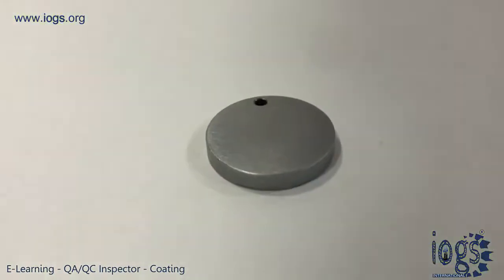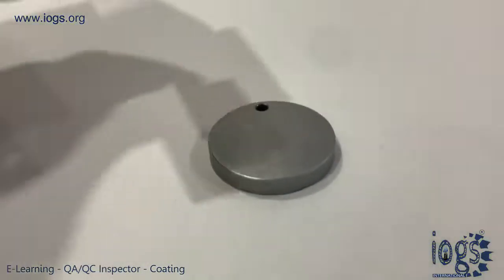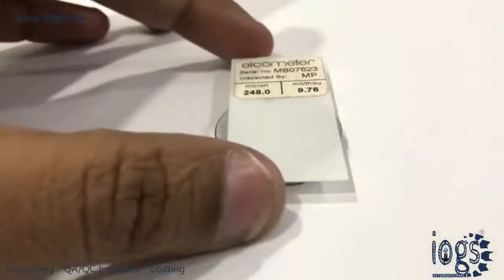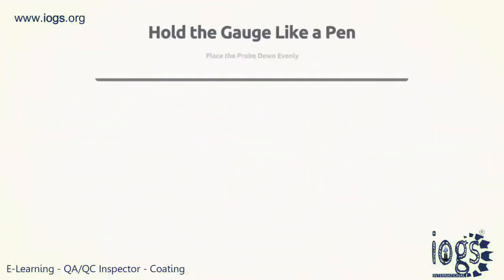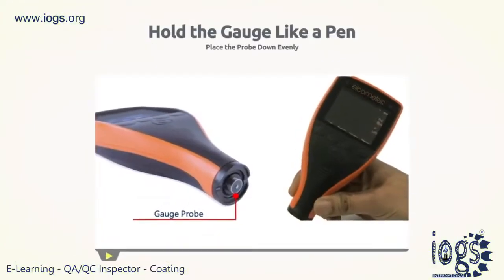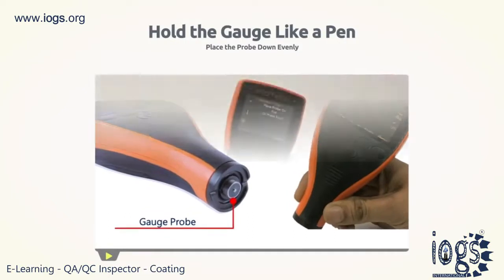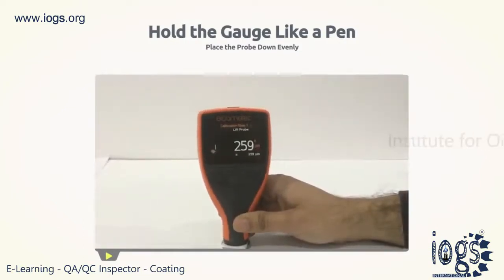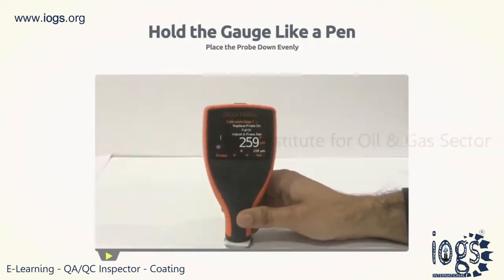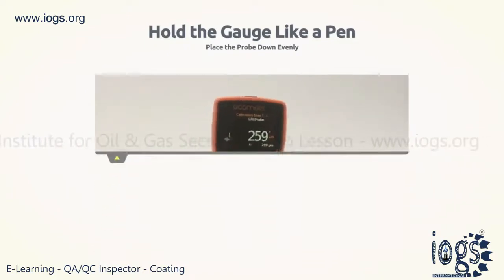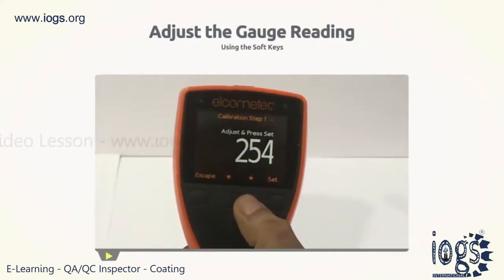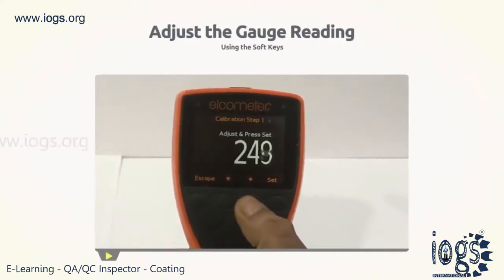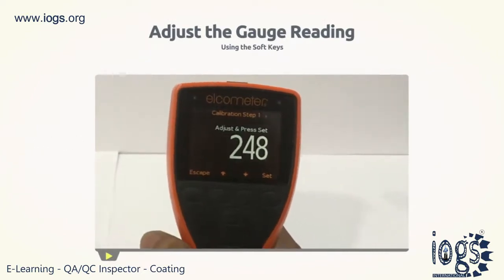The gauge will ask the user to place the probe onto the shim. To do this, keep the shim on the zero plate or uncoated base, hold the gauge probe like a pen, and place down the probe evenly with a 90-degree angle on the shim. Then take the gauge reading on the screen and ensure that it corresponds with the shim thickness. In the case where the readings are different, simply adjust the gauge reading value by using the soft keys. But if they correspond, just press the Set Soft key.